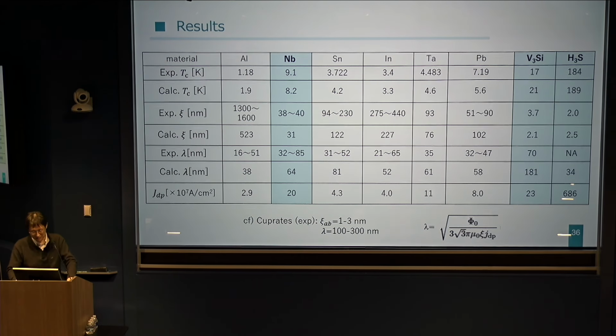But lambda is about 300 nanometers, which is larger than H3S. So from this equation, Xi is similar, but lambda is larger in cuprates. That means JDP should be smaller than H3S. In other words, for H3S, the depairing current is expected to be larger than that of cuprates. So this is a theoretical result.